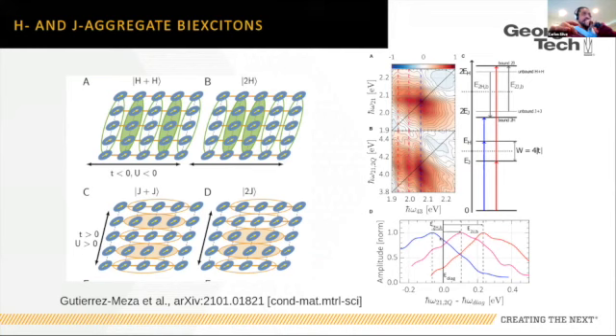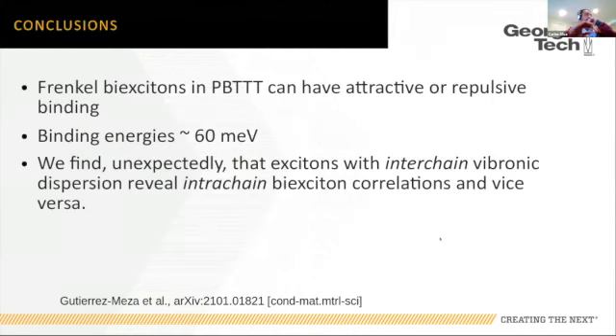So I'm out of time with my 20 minutes, and so I'm just going to skip to these conclusions. What I want to leave you with as a take-home message is that Frenkel biexcitons in PBTTT can have attractive or repulsive binding. The binding energy of the H-like exciton is about 60 millielectron volts, quantified by that 2-quantum measurement. And then we find, and this is really the bit that surprised us, that excitons with interchain vibronic dispersion, what we call an H aggregate, reveal intrachain, so J-like, biexciton correlations, and vice versa.